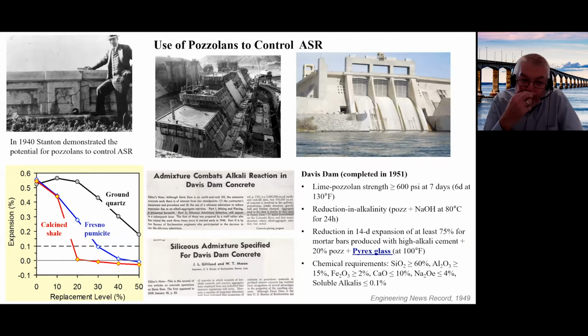Okay, we go back to 1940, when Thomas Stanton first discovered alkali silica reaction. In his landmark paper on ASR, he also discovered that pozzolans could actually control ASR. So we've known this for 80 years, although if you read some of the modern literature, it seems like we're just discovering it. But Stanton demonstrated that both a calcined shale and a Fresno pumicite could be used in his mortar bar test, which eventually became ASTM C227, to control ASR. And shown there as a comparison is ground quartz in the bottom left, ground quartz being an inert material. So you can see that the pozzolans work, that their effect is beyond just mere dilution of the cement.